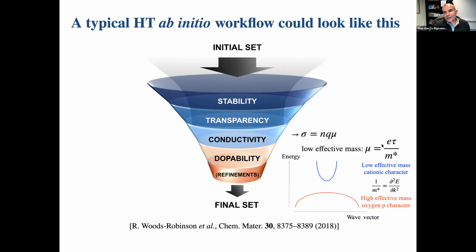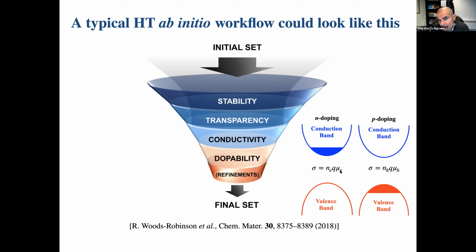And so in terms of transparent conducting materials, there's a difference between the p-type and the n-type. The n-types are usually quite good, with good mobilities, and the p-types are usually quite bad, typically a factor of 10 lower in terms of mobility compared to the n-types. And so the next step is indeed to dope the material, because, as I said, once you have a wide band gap, it's not conducting. To make it conducting, you want to dope slightly in such a way that you have enough carriers, be it electrons, like in the case of n-doping, or holes, like in the case of p-doping.